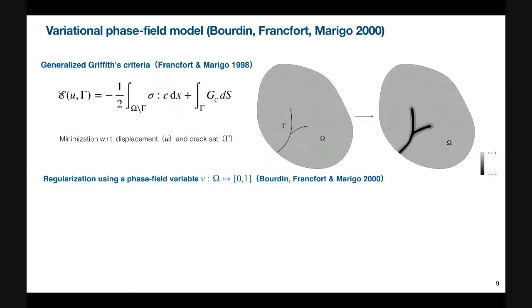So in this figure, we have a discrete crack, and gamma represents this discrete crack. By introducing a phase field variable, this sharp image of the crack is blurred or diffused in the phase field representation. Instead of this binary representation of the crack, now we have a smooth or diffused representation. The phase field variable is zero along the crack and one away from the crack. But instead of crack or not crack, zero or one, it can have a value between zero and one.